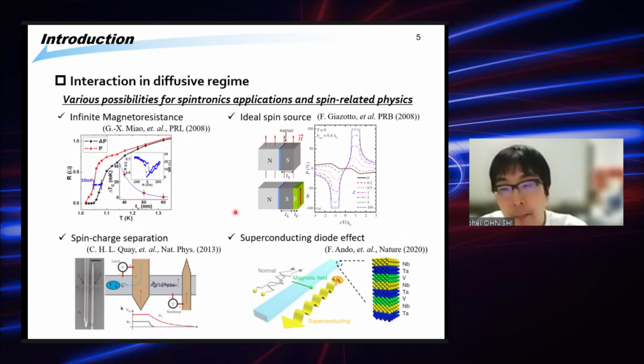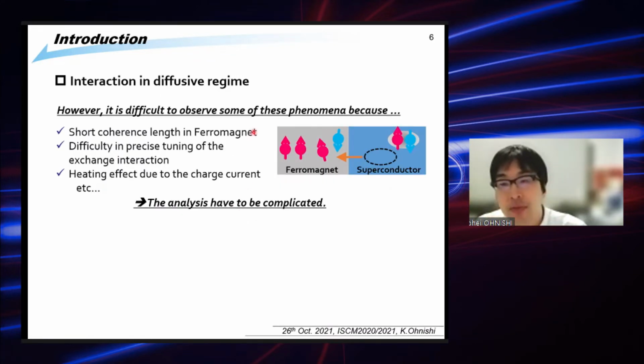However, in some cases it is difficult to observe these phenomena, because in the direct contact of ferromagnet and superconductor, of course there is a superconducting proximity effect in the ferromagnet, but the coherence length of this proximity effect in the ferromagnet is very short. And also the exchange interaction in the ferromagnet can easily break the superconductivity at the interface. So it is better to tune and control the exchange interaction in the ferromagnet precisely to measure these phenomena systematically.